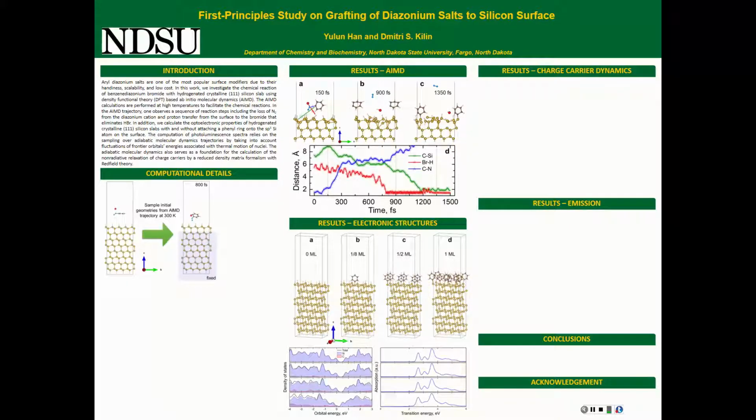If you try to do the same numerical experiment, you'll see that the time from launch of your reaction until something chemically happens is non-linear and drastically depends on temperature. If you use realistic temperatures, you may need to run your simulation for like 100 picoseconds, which is impossible for ab initio molecular dynamics.